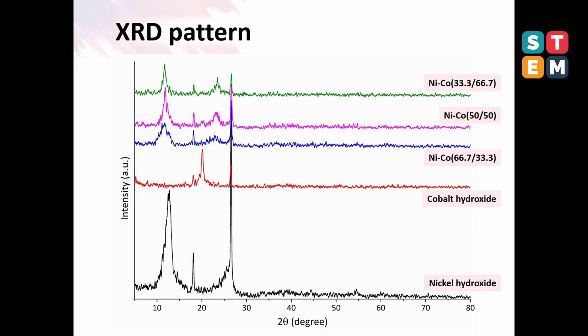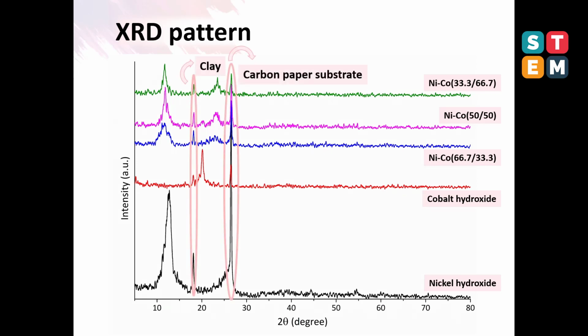All mixtures of nickel and cobalt hydroxide exhibit both peaks of nickel and cobalt hydroxide. This result confirms successful synthesis by hydrothermal treatment. We note the sharp peaks around 18 and 26 degrees 2 theta are from the clay support and carbon paper substrate.